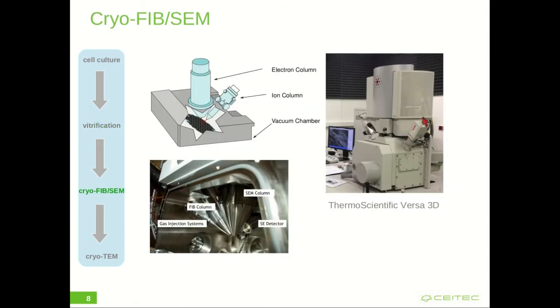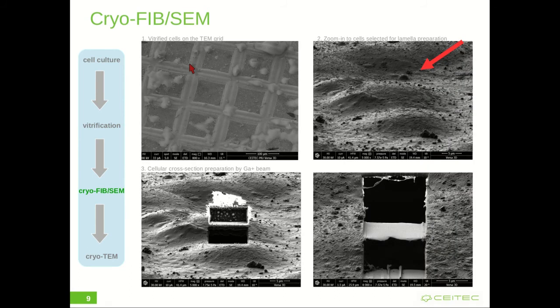Following the success of the vitrification, the sample is transferred into the dual beam microscope. The instrument constitutes a scanning electron microscope column and the ion column, which focuses the current of gallium ions on the sample. The preparation workflow consists of a localization of the cells, ideally in the center of the grid square, and gradual removal of the cellular material by scanning with FIB in order to retain a thin cellular section, which is then electron transparent for TEM.